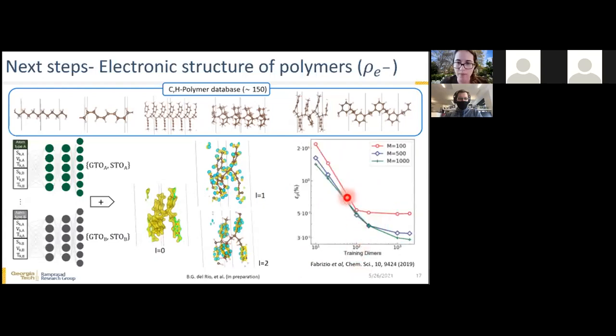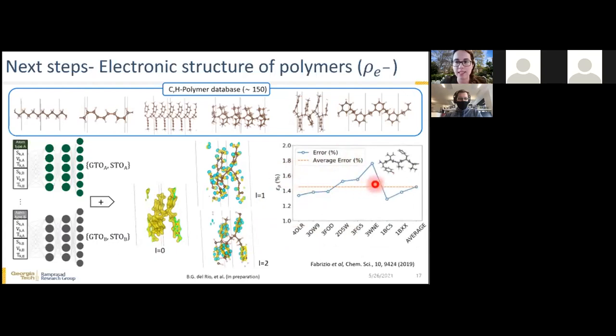And even though they obtain very low error percentages always, it's important to note that they are using the core density also. So it's not just the valence density. And the valence density is the one where most of the error is going to come from because of this delocalization. So the total number of electrons that they are dividing by to get the percentage error is much higher than if they were just using the valence electrons. However, another thing is that once they go to larger molecules, this error significantly increases, which poses concerns regarding the transferability of this model to even larger systems, because at the end, that's what we're interested in using it for: very large systems where DFT cannot be used.